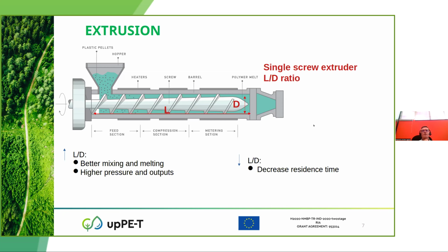Longer screws tend to generate higher pressures, and regarding material processing, the optimal L/D ratio varies depending on the type of polymer being processed. Some polymers require longer screws for adequate melting and mixing, while others may be processed well with shorter screws. In summary, the L/D ratio is a critical factor in extruder design, influencing mixing, melting, output, and pressure. The appropriate ratio depends heavily on the polymer being processed and the desired outcome.